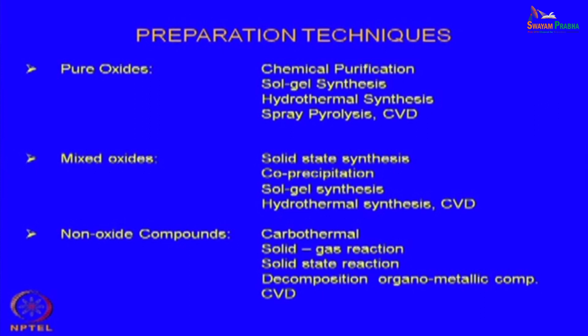in an inert atmosphere, so that the carbon does not get oxidized in presence of oxygen. So, oxygen should not be allowed when the reaction is going on. If you are talking about nitrides or even carbides, carbon can be taken in the form of solid carbon, or gaseous, maybe carbon monoxide or some hydrocarbons. Hydrocarbons can be taken as a source of carbon and then it can be allowed to react with some metals, so that the carbides can be formed.